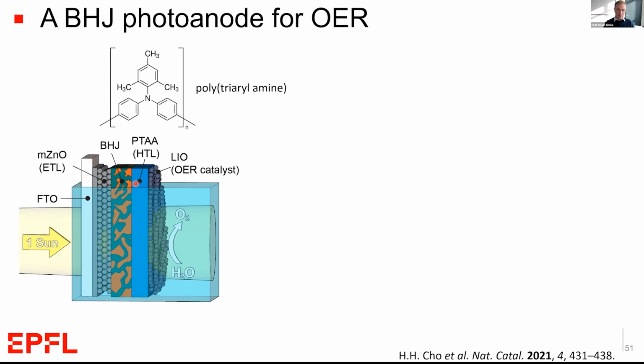Using this hole transport layer helped to extract the charge carriers quickly so they don't accumulate in the bulk heterojunction. This is a big problem because the oxygen evolution reaction is kinetically very, very slow. And in other systems, especially the oxide photoelectrodes, a large amount of charge accumulation in the semiconductor itself is necessary to develop the photopotentials that can drive the OER reaction. We also need that in our bulk heterojunction system, but if we accumulate the charge carriers in the bulk heterojunction, then those charge carriers will probably just oxidize the organic itself, which we want to avoid. So we have to get those charge carriers out with this PTAA hole transport layer, and then they feed them to the catalyst. So that was the second way we improved the stability in this photoanode.